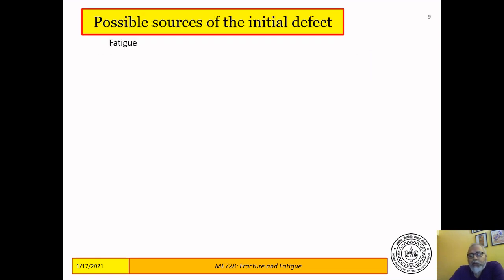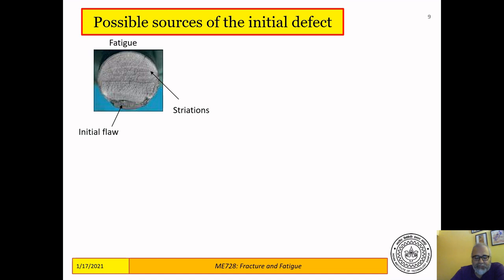Some defects appear during operation, and one of the ways in which defects do appear is through fatigue. Fatigue leads to development of large defects from small defects over a very long period of operation. So this is the cross section of a shaft, and as you can see, this shaft had for some reason a small initial flaw.